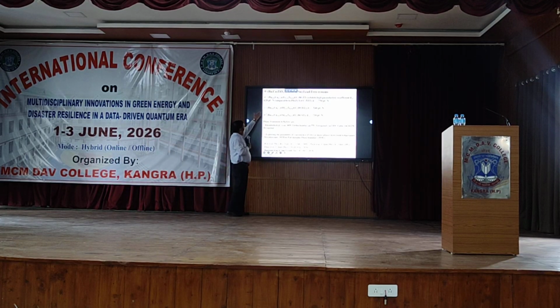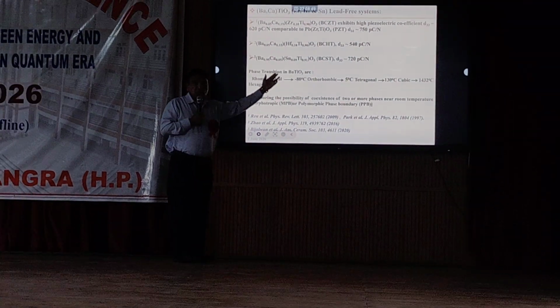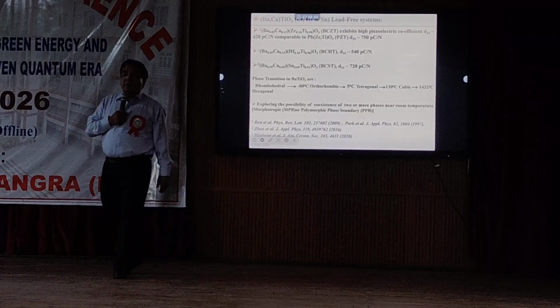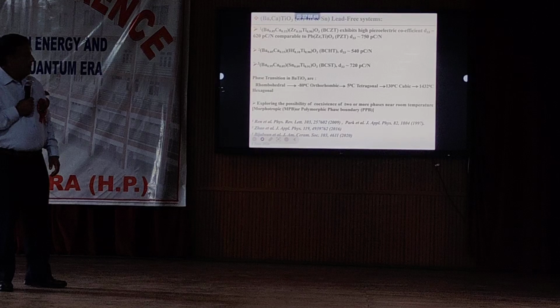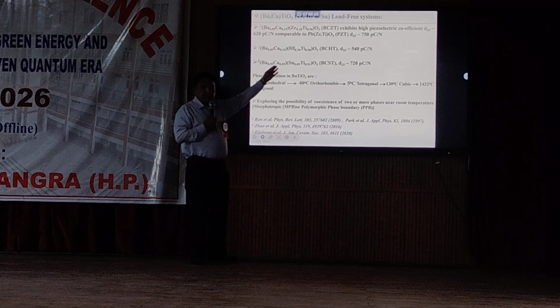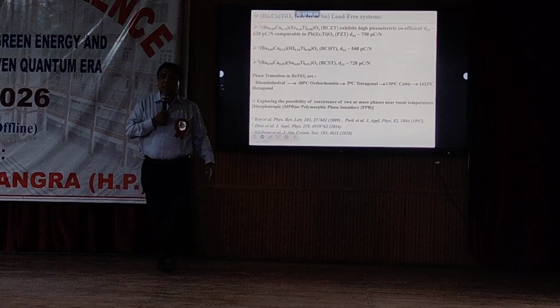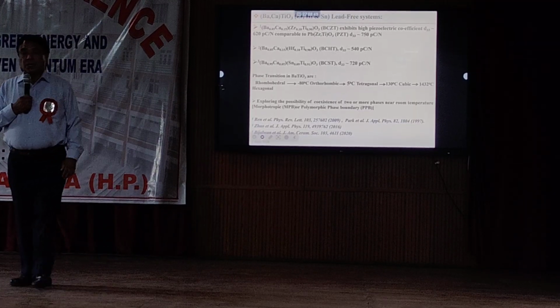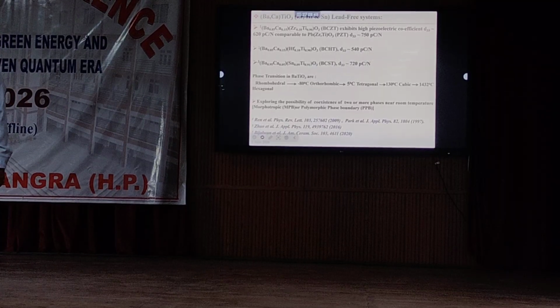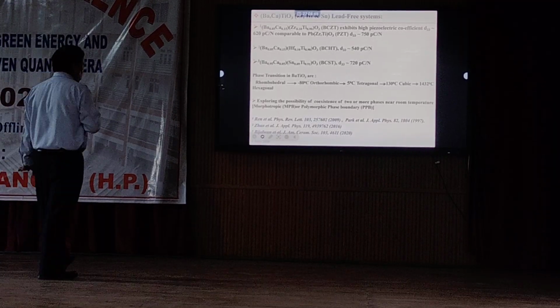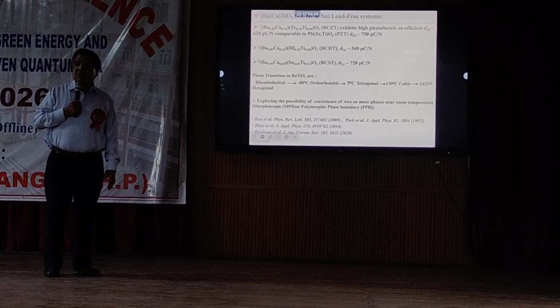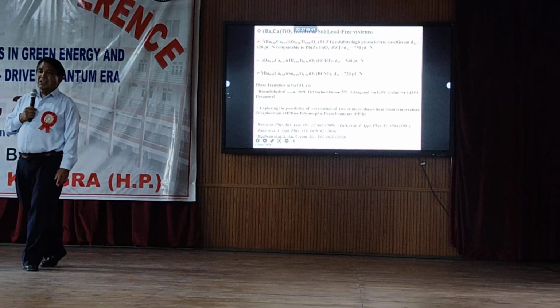So I have listed here 1, 2, 3 from these references. All these are A and B site modified barium titanate, and these compositions are morphotropic phase boundary compositions, having a piezoelectric coefficient of 620 picocoulomb per newton, which is comparable with that of lead zirconate titanate, and a similar situation with the other two compositions. Piezoelectric property is very crucial when we talk about designing sensor and actuator kinds of devices. So achieving a morphotropic phase boundary and polymorphic phase boundary is very critical so as to enhance the polarization, and enhance the ferroelectric, piezoelectric and pyroelectric properties.